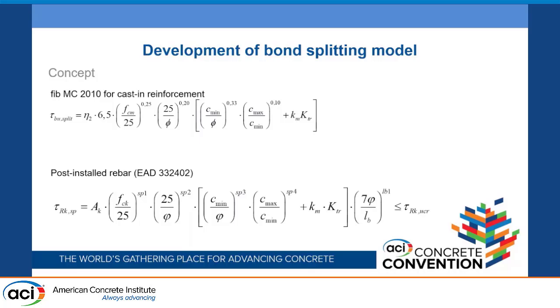Then we considered the concept given in fib Model Code 2010, which was available for cast-in reinforcement. They had a model where the bond splitting strength is a function of the concrete strength, the rebar diameter, minimum cover, maximum cover, and the transverse reinforcement. So let's do a similar kind of thing.